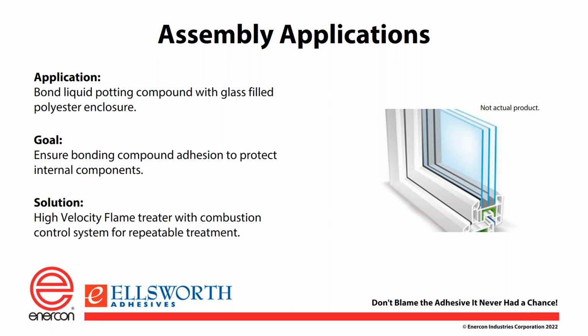You can see the side profile of that particular glass or window. There's always a very unique profile depending on the manufacturer, and so sometimes you have to create different manufacturing tools to get down in there. But again, this is another good bonding application. You're usually using a PVC or some other plastic for the window, which is again low surface energy, so treatment is necessary to get the good bond.